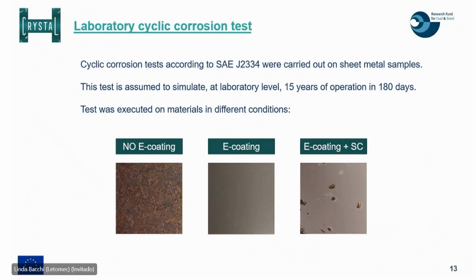As already mentioned by Sílvia, we planned to perform measurement during 4 live tests. This was not possible due to several reasons, but we substituted this testing with the cyclic corrosion test, which is a laboratory test, but can represent, however, in 6 months, the same of 15 years of operation. So we realized some coupons that were small sheets, maybe 100 by 200 millimeters, and we put them in the cyclic corrosion test according to the standard.